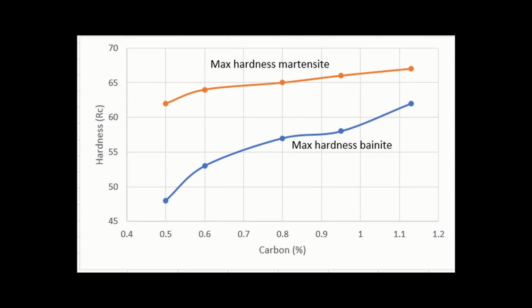One of the disadvantages of bainite is that it's usually lower in hardness than martensite. If we look at max hardness martensite, where we just quench to room temperature and measure the hardness, even a 0.5% carbon steel is over 60 Rockwell. Once we get to 0.6% carbon and higher, we're talking 64, 65, 66 Rockwell C as quenched. And even after tempering, the hardness can still be over 60 Rockwell.